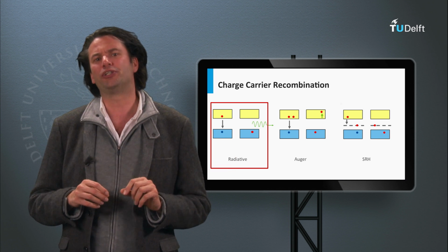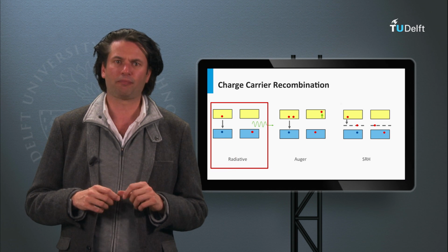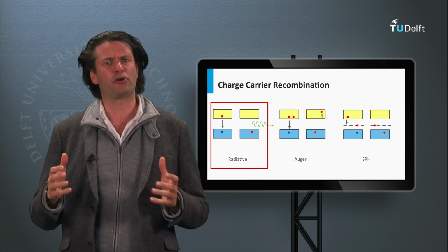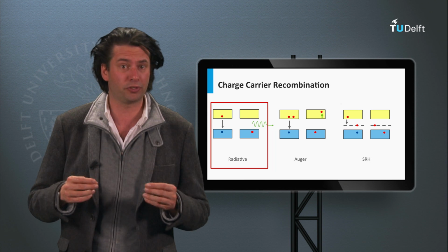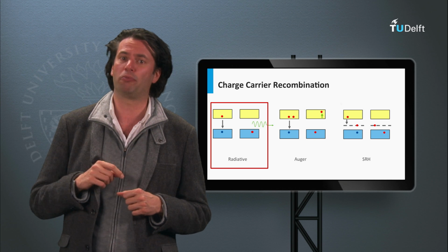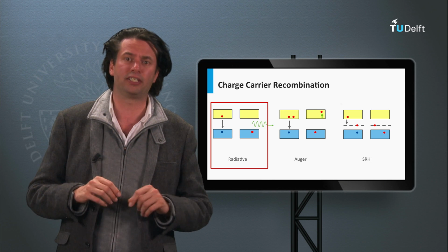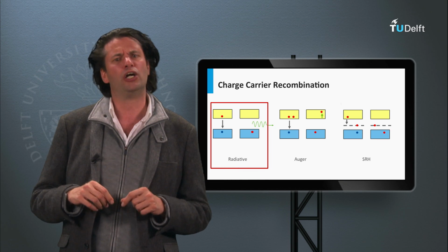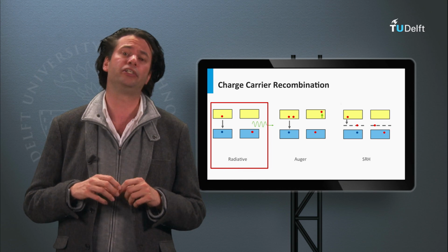If we look at the utilization of the bandgap energy, due to the direct bandgap properties, radiative recombination processes can become an important recombination mechanism as well. The Shockley-Read-Hall recombination can be kept low as the typical epitaxy processes used to deposit 3-5 films results in high purity films.